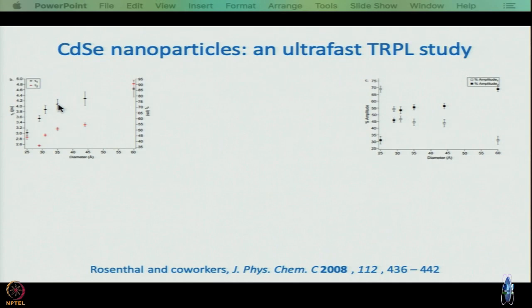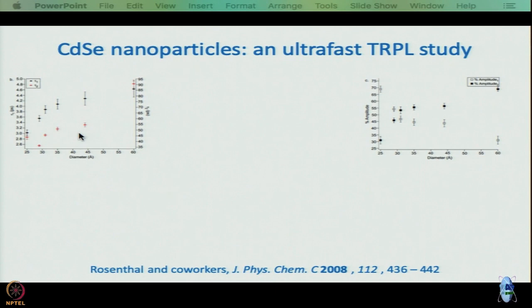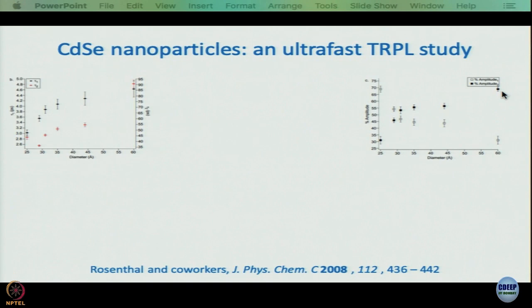Both lifetimes actually increase as the size of the nanoparticle increases. One axis shows the shorter lifetime and one shows the longer lifetime. The amplitude of the short component decreases as diameter increases, while the amplitude of the relatively longer component increases with increasing diameter.